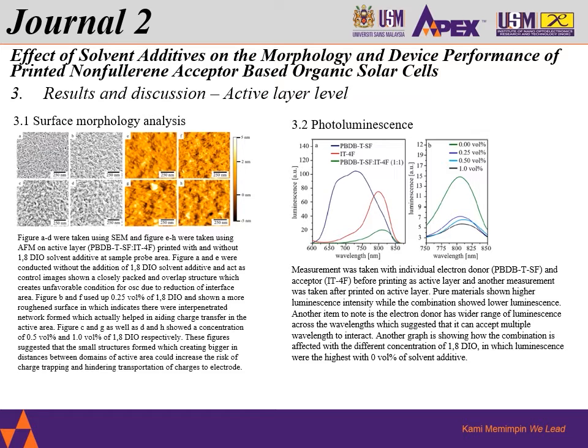Next, let's take a look at the photoluminescence results that were measured. Over here, we have the pure donor and the pure acceptor, as well as the blend acceptor donor solution, reported using wavelength as well as luminescence. On the right-hand side, it shows how different volume is affecting the luminescence as well. Pure materials show higher luminescence intensity, while the blend shows lower luminescence.